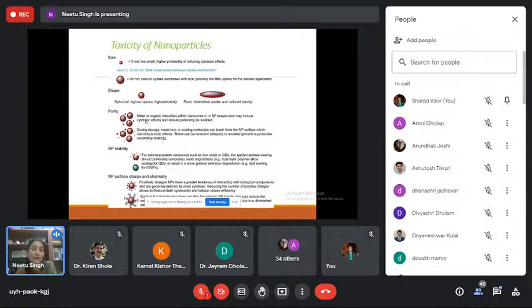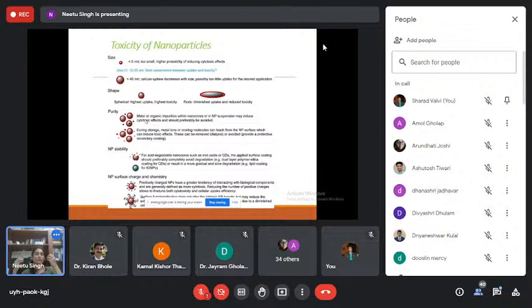Then, nanoparticle stability is also important for toxicity. For example, suppose something is degrading, and the degraded product is toxic, and this degradation gets enhanced in the presence of low or high pH. For example, acid catalyzed hydrolysis. Okay, so if there is inflammation, the pH is really low, and if this material goes into the region of inflammation, the hydrolysis will start happening really fast. Because of that, the byproducts of hydrolysis come faster than anticipated, and that will cause toxicity. So stability of the nanoparticle is also extremely important.